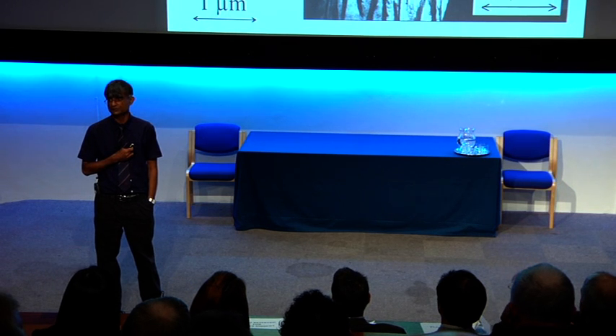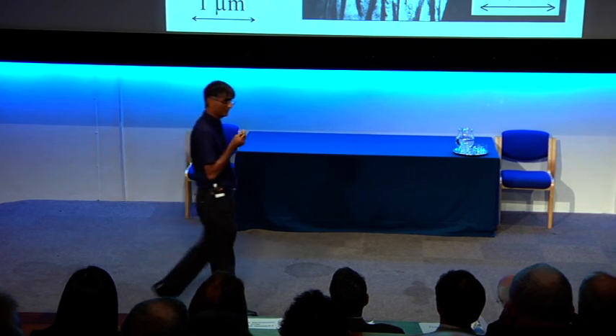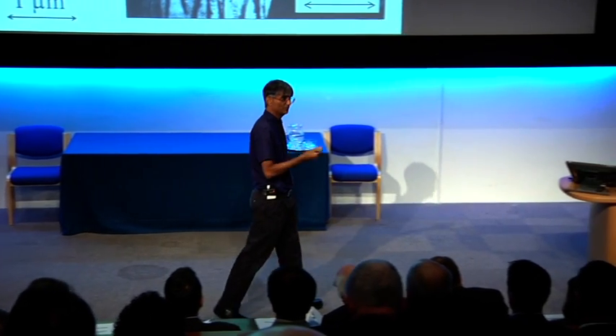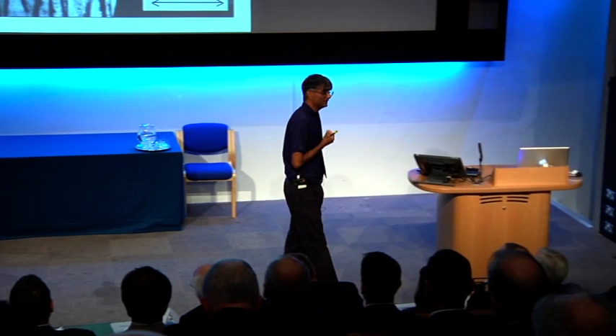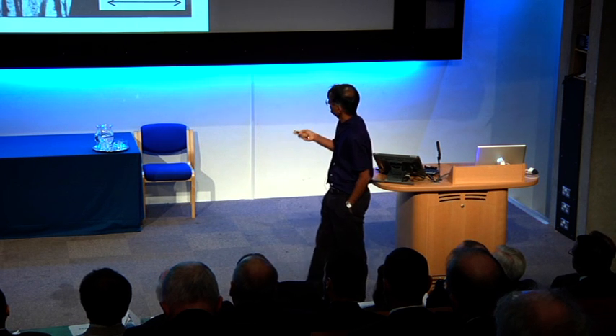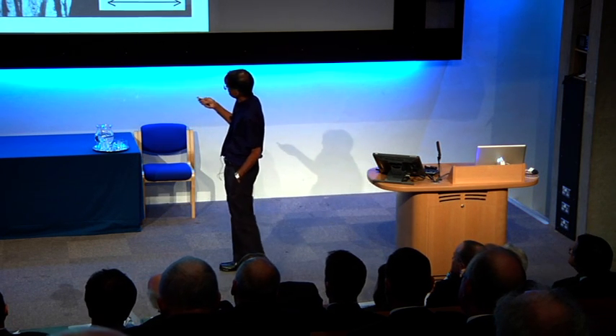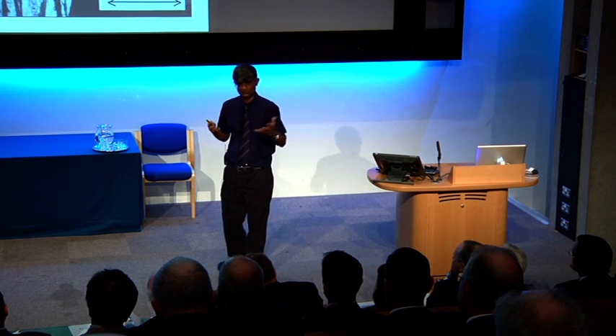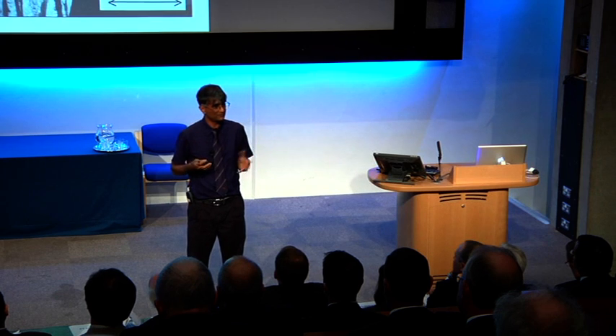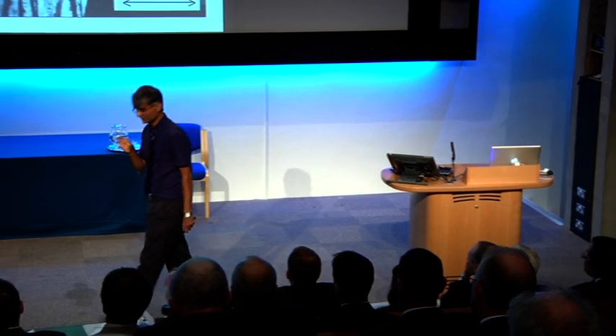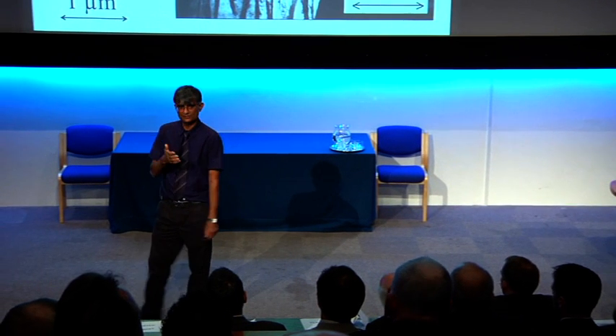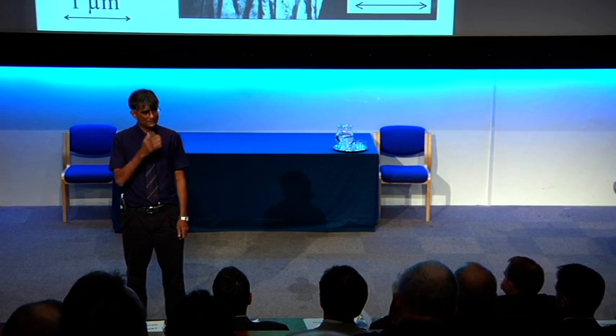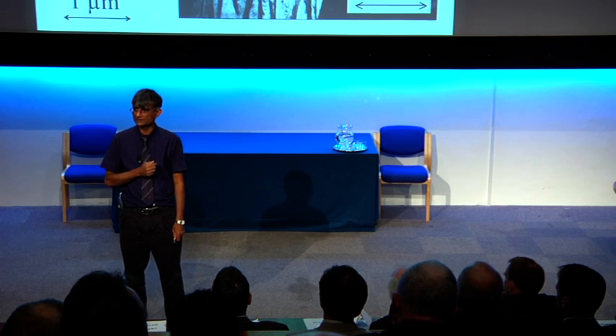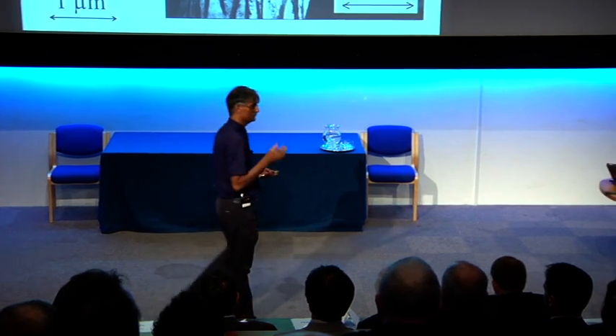Instead of having the conventional cementite, you end up with regions of austenite. Now, austenite is a good phase to have. It's an expensive phase in normal stainless steel because you have to add nickel. Here, we are making it extremely cheap by using the carbon that is rejected from the ferrite. And it's a very stable phase because the partitioned carbon has a concentration of the order of 1.28% to 1.48% inside the austenite. So we have a beautiful microstructure, which is alternating plates in three dimensions of very fine ferrite separated by very nice films of retained austenite, which has a toughness.